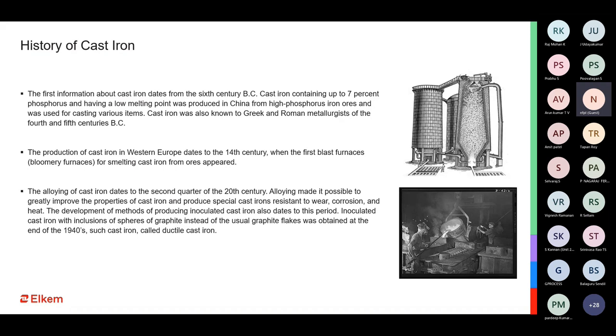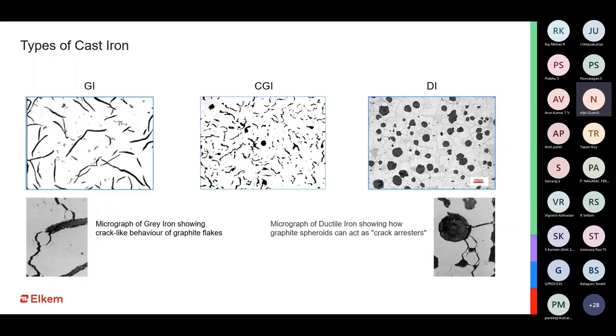After that, the graphite, which was initially in the form of flakes, was gradually converted into something more spherical in shape, which is nodular iron, ductile iron, which gave us much better mechanical properties, especially compared to the earlier gray irons. But we did not stop just by producing ductile iron. The industry came up with much more advanced grades of iron, developed to meet the ever-growing application requirements of the industry. One such was the production of CG iron, which is nothing but a midway or a mix of both gray iron and ductile iron.